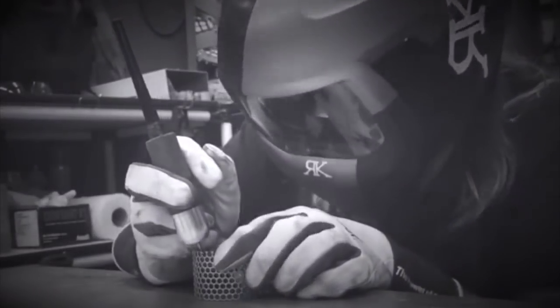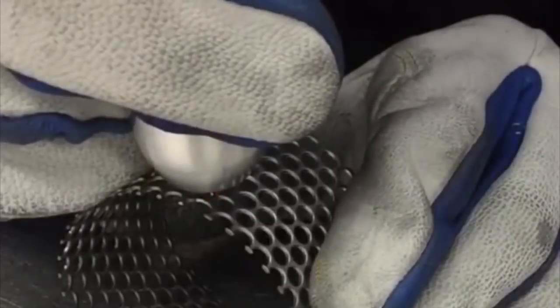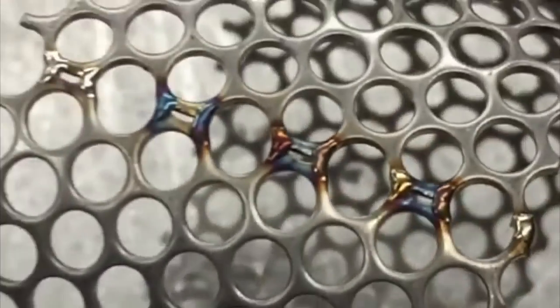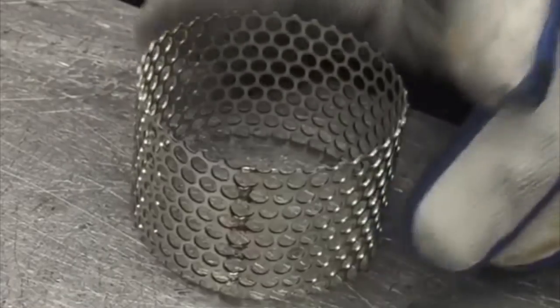Mm-hmm. So you probably, after 30 seconds or 45 seconds, could lay your hand on it with that water circulating through there? After the welding's done, they're still a little bit too hot to touch barehanded, but about a minute and a half after, you can grab those barehanded. They'd be a little bit warm, but it starts to cool them down really quick.